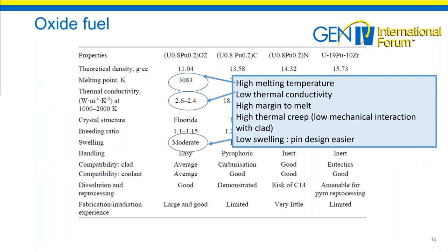On the oxide fuel, with regard to the mixed oxide fuel, the principal features are low thermal conductivity compensated by high melting temperature. A special design such as a central hole in the pellet leads to a higher margin to melt, and this allows higher power. Hopefully, this high temperature above 2000 degrees generates a total release of fission gases and thus minimizes the gaseous swelling. Solid swelling is low, half the value compared to the metal and carbide fuels. And the thermal creep is also very efficient at this temperature and therefore reduces the mechanical interaction with the cladding.